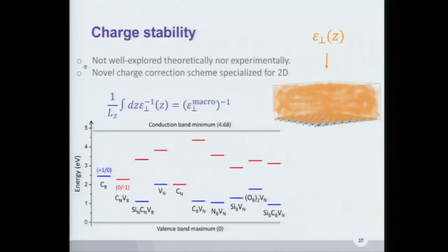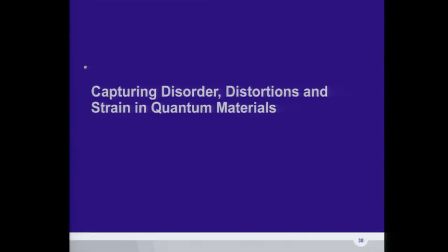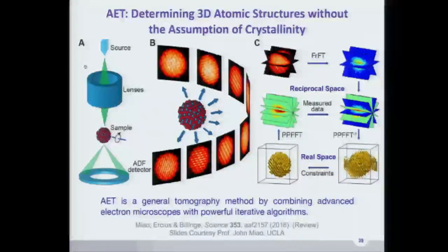From a theory standpoint, hBN is challenging. You need to think about how you will include charge stability. The fact that in a truly monolayer material, it's actually hard to think about what it means to have a well-defined epsilon, both in and out of plane. So we have charge correction schemes that have been implemented in our code, especially for 2D materials. And these are now being leveraged for us to think about defects in lots of other 2D materials, not just hBN. I will just briefly touch on this, and then I promise I will conclude right after this.